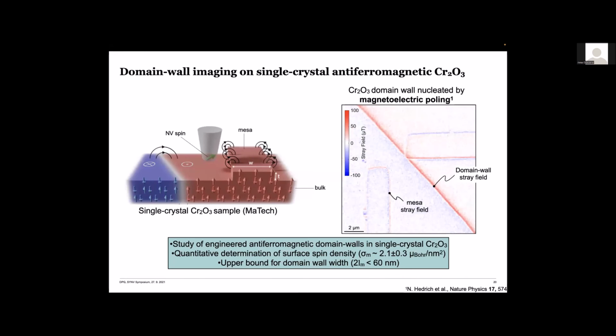More recently, we were interested in studying the more fundamental properties of these materials, and therefore turned our attention to single crystal samples. And there, our motivation was to nucleate individual domain walls using the magnetoelectric effect. So I'll skip the details of that, and then study the properties of these domain walls. And that's something that worked.